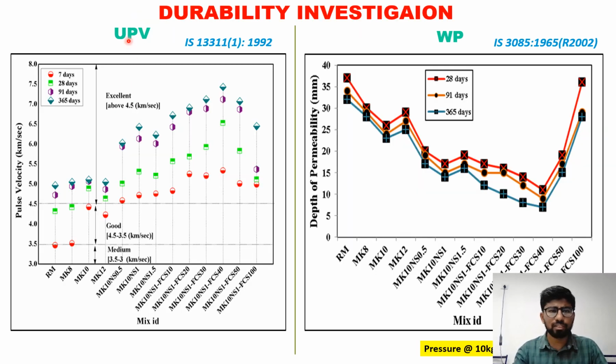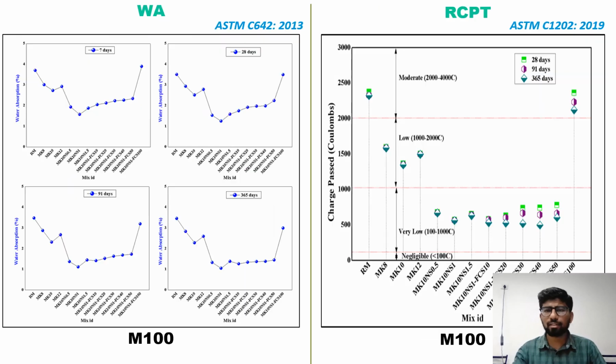Which reflects in the durability results, where we can see FCS 40 has high density, and it also allows the high pulse velocity to pass. In later age also, the hydration reflects in these results. Coming to the water permeability, which is related to the connectivity of pores, the connectivity of pores has been reduced until the 60-40 proportion of ferrochrome slag and C-sand. The water absorption also follows a similar pattern. And the RCPT value slightly increases while replacing the ferrochrome slag. This is due to the conductive ionic species present in the slag.